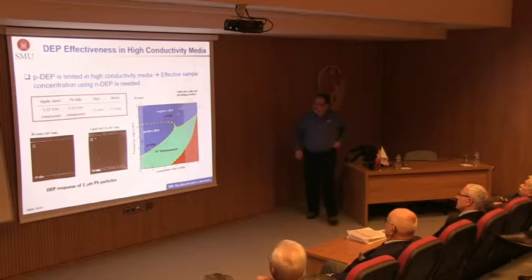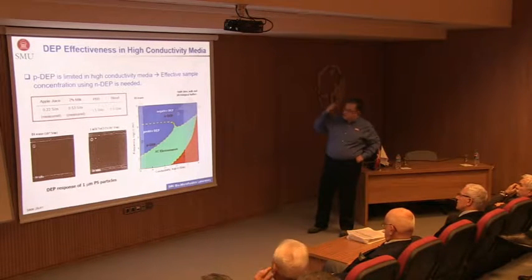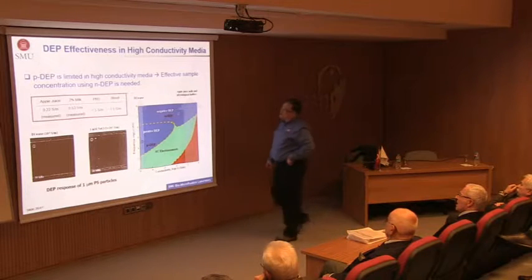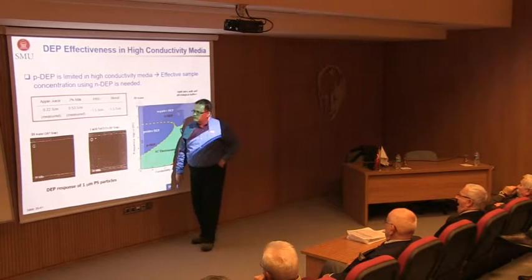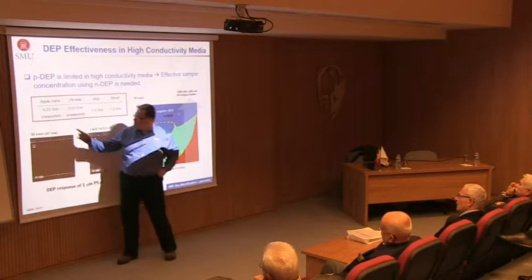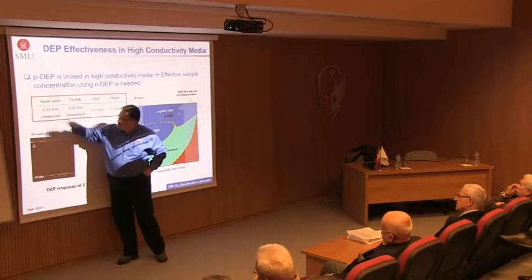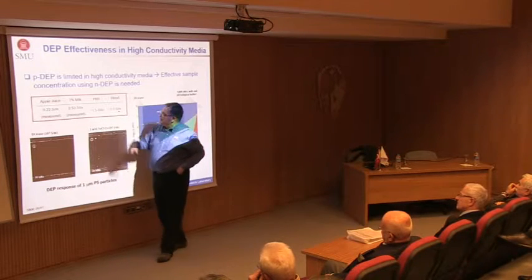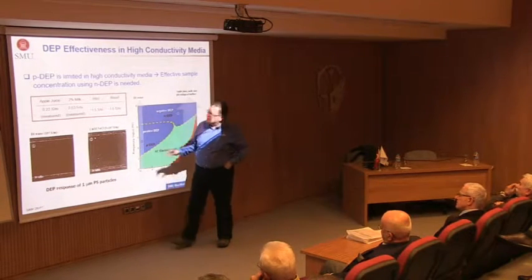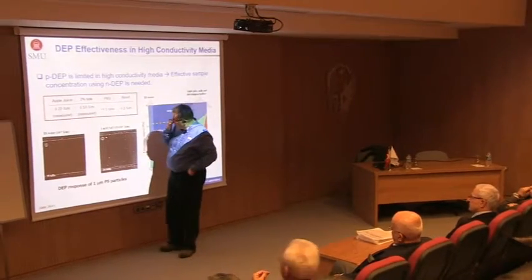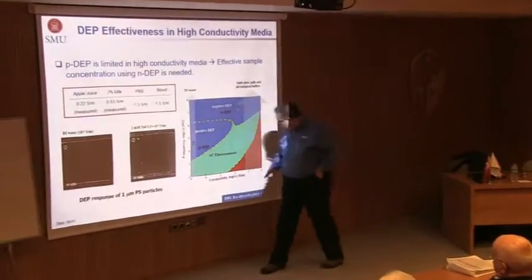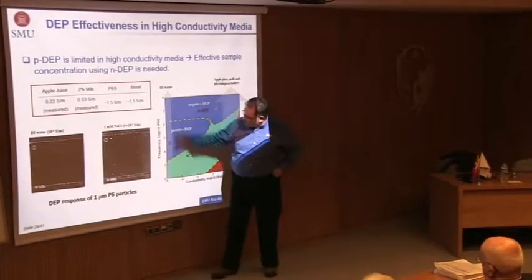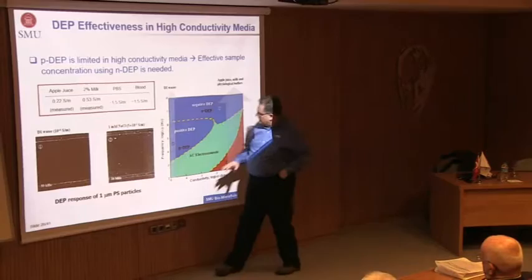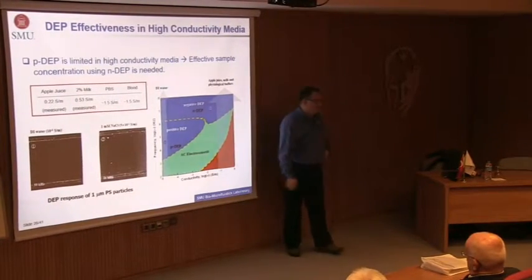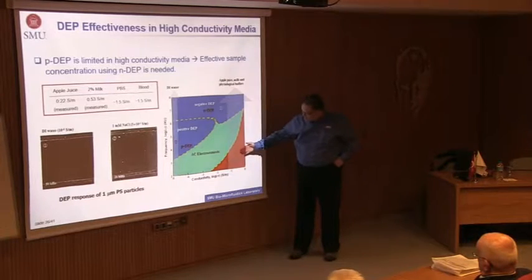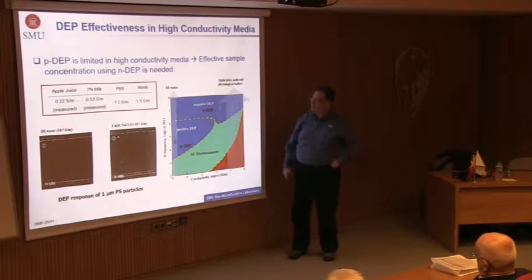So what we realize here is that DEP is great. You can see positive and negative DEP response, but most of the applications are happening in high conductivity solutions. Like, we were interested in food and beverage safety, so this is basically 0.2 Siemens per meter. Blood, or the PBS solution, physiological buffer, is 1.5 Siemens per meter. Indeed, what we expect is, at lower concentrations, everything worked well. At higher concentration, you have nothing but negative DEP. Or, of course, Brownian, AC electroosmosis and negative DEP.